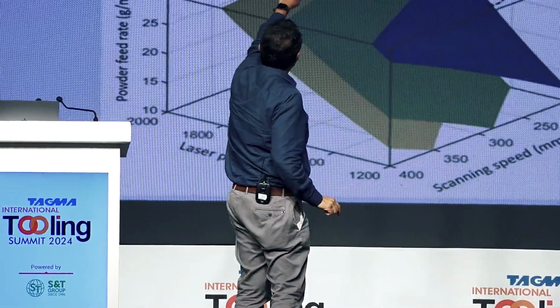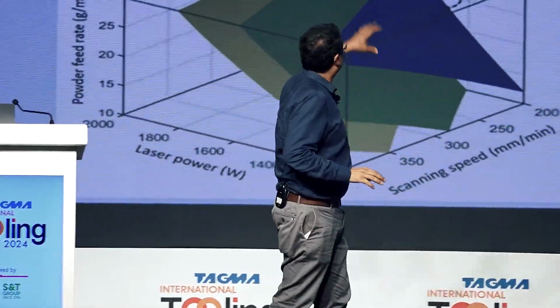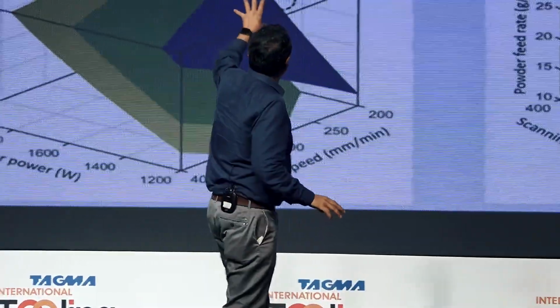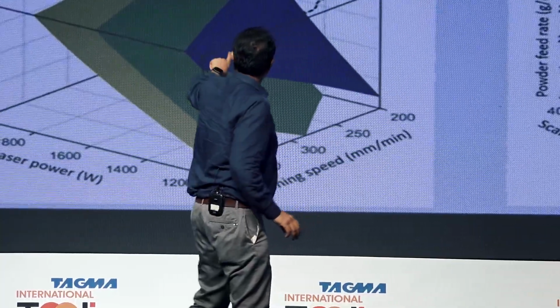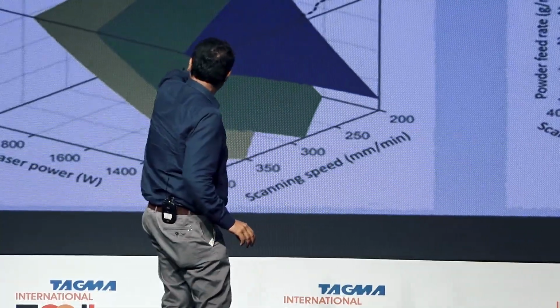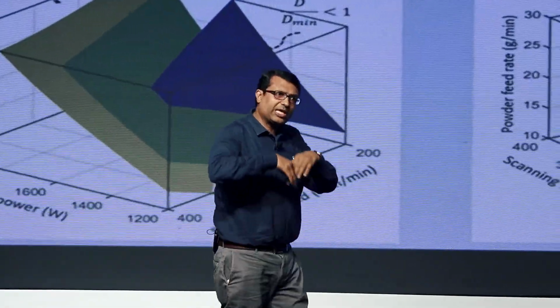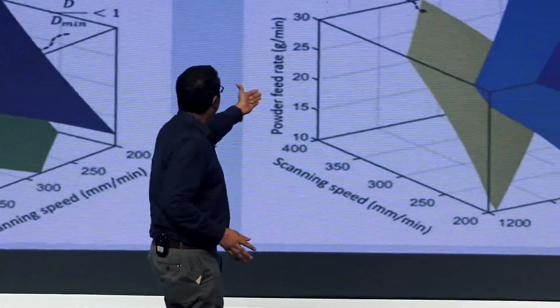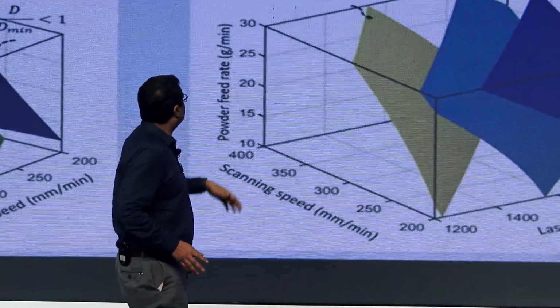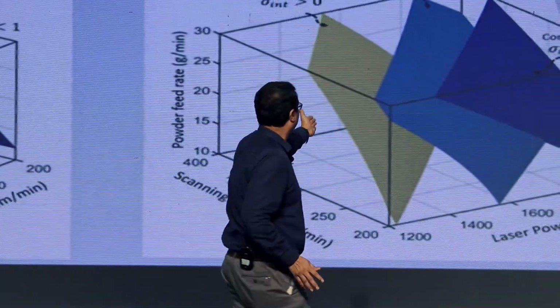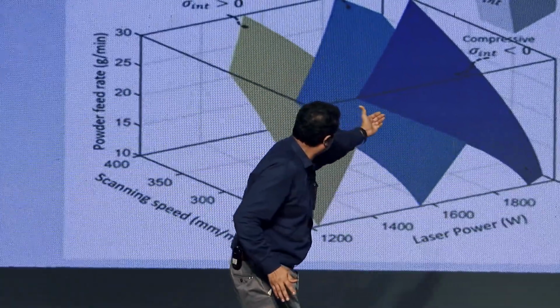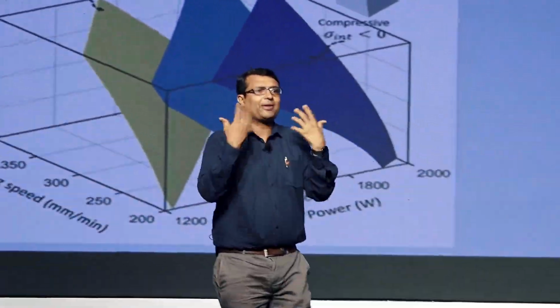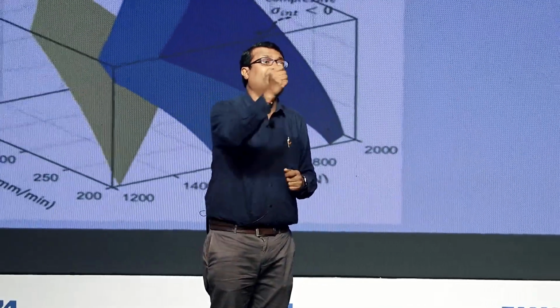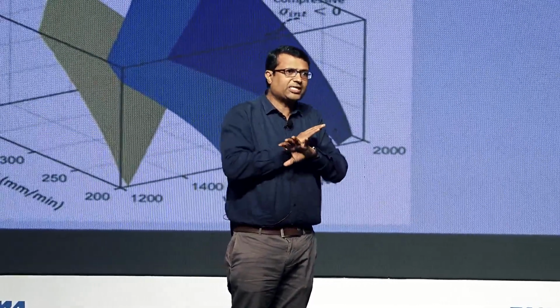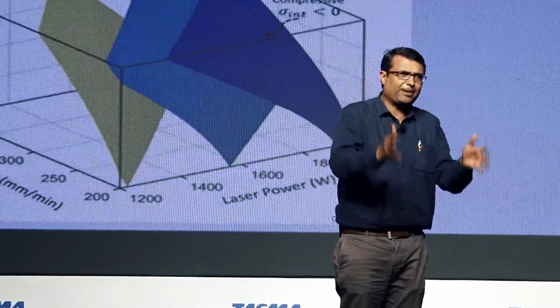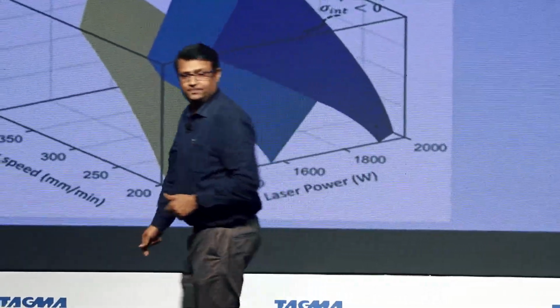So in the top map, if I go to this laser power and scan speed combination, I get favorable deposits. If D over D min is greater than 1, the green and below are favorable deposits. And finally, the blue and green side shows compressive stresses. If I go from sigma int less than 0 to this, this combination would give me favorable compressive stresses. So all these simulations are giving me process parameters to work with. This is not just intellectual stimulation; these are functional process parameters which I can use on a real machine.